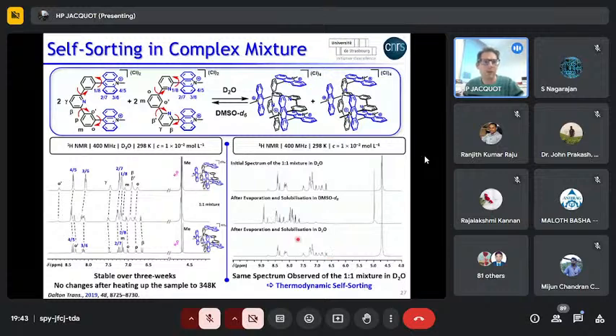And this was very surprising to us because we have tweezers of the same size, the same shape, and involving the same kind of interactions. But what we know is that this new dimer formation has a binding constant which is lower than the previous one. And if you do the math, only one order of magnitude is enough to drive the formation of the homodimer AA, and then only B molecules can interact with B molecules to form the homodimer BB. Also, the DFT calculations told us that we have a more favored interaction between the nitrogen and this CH bond, kind of like an electrostatic interaction, which is more stabilizing than for the other tweezer.